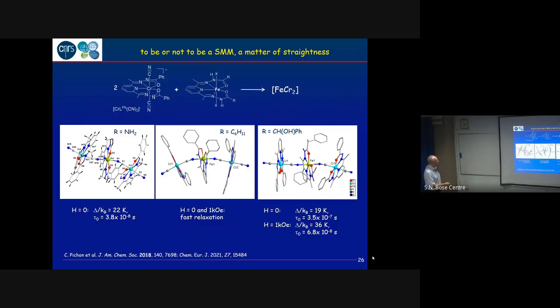The only difference, as you can see, is that the molecules are more or less linear or a little bit more bent. And if we look, for instance, at the angle we have here between the carbon, nitrogen, and the iron, you see that we don't have something that is linear, and it is more or less planar. But usually people consider that this has no real importance. Such a bending should not have an effect on exchange interaction and on anisotropy. But